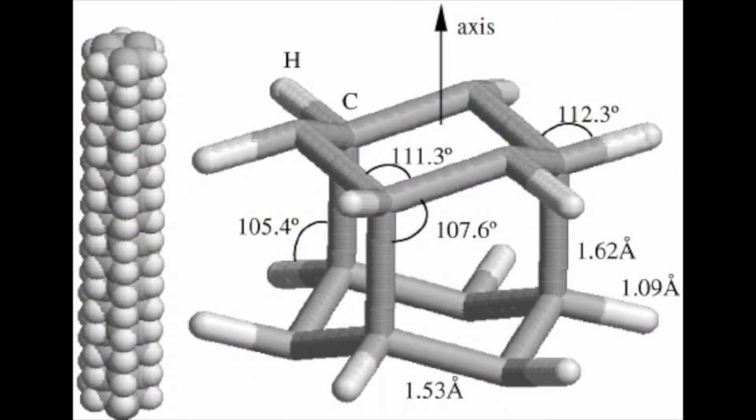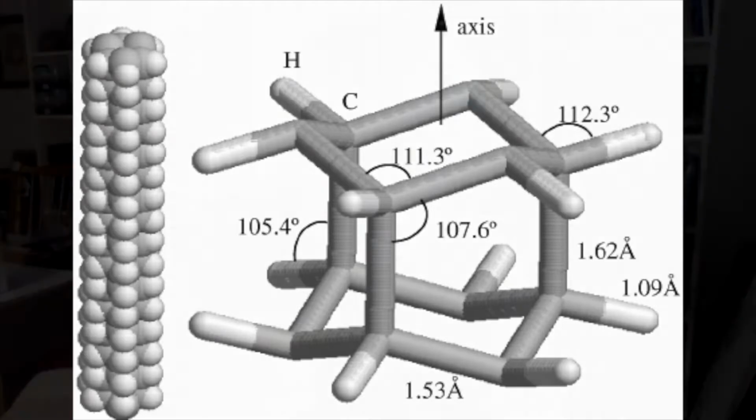I knew that there was cyclohexane, and that it was very happy, because I'd been spending many years thinking about carbon 6-fold rings for nanotubes and fullerenes and graphene, although graphene came later. And so I thought, if I just say every sp3 carbon can only make 3 bonds to neighboring carbons, and I say the 4th bond is used up somehow, then it makes 6-fold rings with 3-fold vertices, which are the mathematical rules you need to make all of the fullerenes, the nanotubes and the closed shells and everything else.